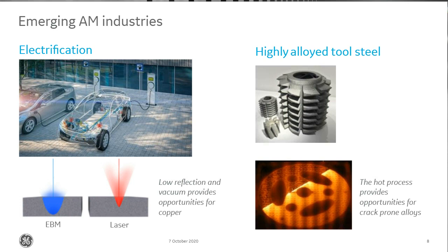Yeah. So one of the things we are looking for in copper when it comes to electrification is conductivity. And basically, you can say that the conductivity of copper is very much dependent on its oxygen content. So with the vacuum environment where we melt and form the components, we're able to produce parts with an extremely low oxygen content. That means you get less thermal losses in your components, which is extremely important for that industry.